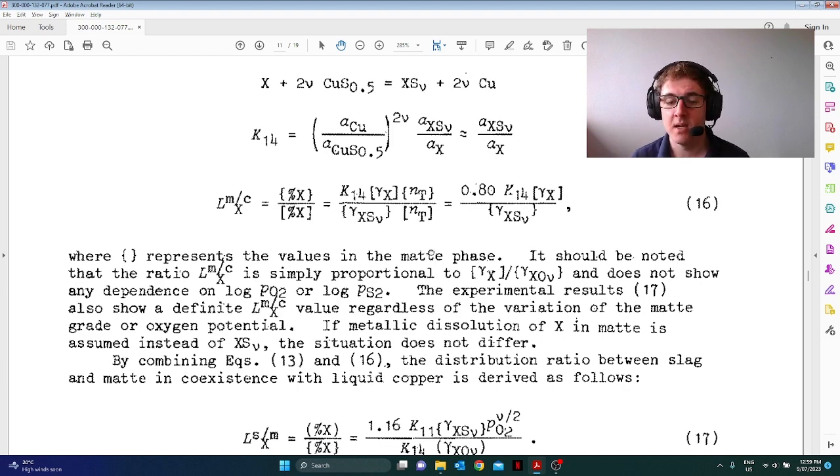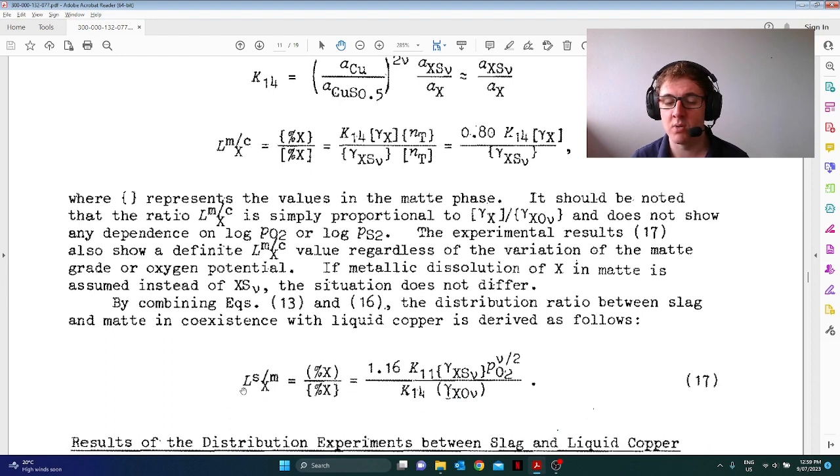So what happens is this distribution ratio. This distribution ratio is somewhat fixed at certain conditions. So for the same product grades and slag targets, your distribution ratio does not change much at all. And it's because it all ties back to your composition. So the distribution ratio comes from reaction equilibria, and you can see here that it depends on your equilibrium constants and your activity coefficients. These activity coefficients will vary a bit with the composition of your phases as well as temperature. And your PO2 only really changes with your chemical targets there. So everything ties back really nicely to PO2.